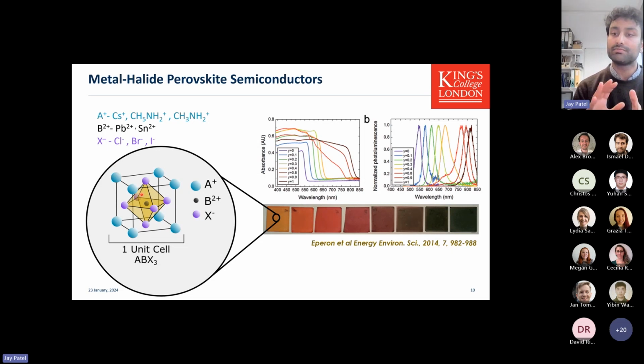You have a central metal cation that's either lead or tin, and you have these halides that are at the faces of this cube. This material has actually proven to be very, very tunable. As you can see in the figure on the right, you can change these different elemental compositions, and you can actually start to absorb different colors of light.